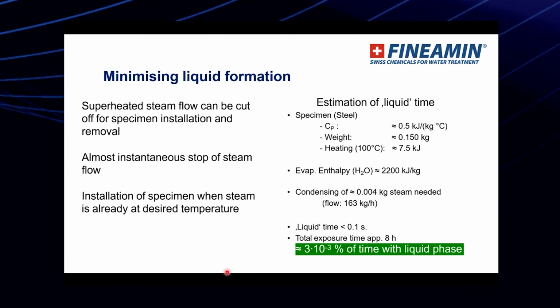And if you take the total exposure time, approximately 8 hours during the experiment, it's 0.1% of the time with liquid phase. So it's really insignificant. Of course, this is with the estimation that the heat capacity of the dry steam before condensing is not considered. Based on this assumption, we can say the liquid phase is insignificant, so this is a completely dry steam. So when the FFA absorbs, it is on the dry steam.